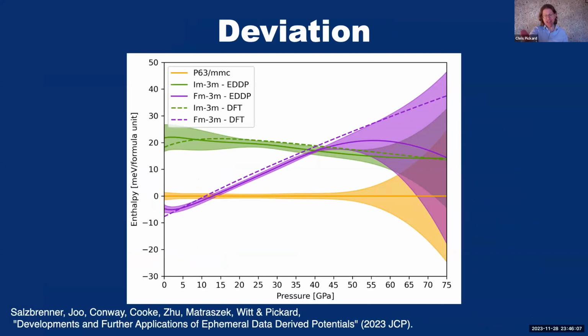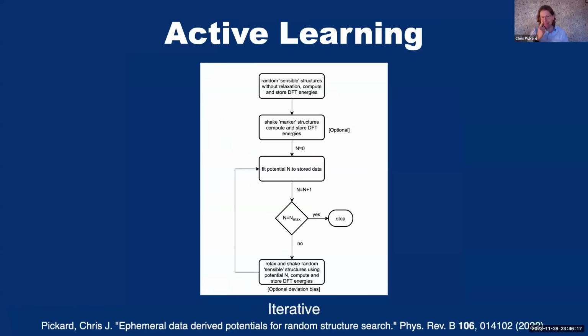You can see in this case here, we've trained the potential up to 50 gigapascals, and after that, it doesn't really know what it's doing. And we can see that clearly from the data. But the nice thing about this as well is that we can embed this in an active learning scheme, so we know when we don't know very much about a particular configuration, and we can bias the active learning scheme towards those high deviation parts of the landscape.